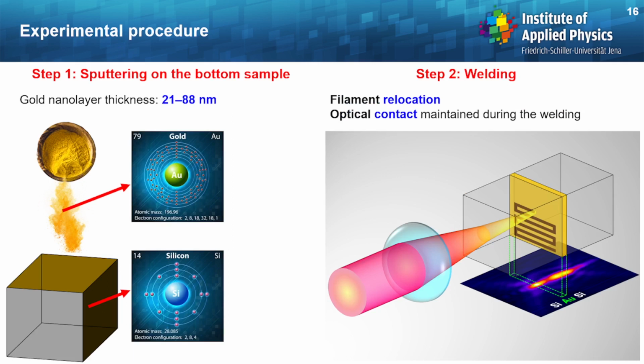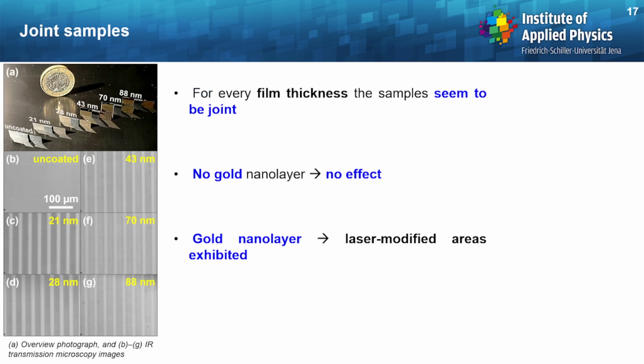So, basically the experimental procedure is now quite straightforward. First we do some sputtering on the bottom sample with gold nanolayer thicknesses between, let's say, 20 and 90 nanometers. And as a second step, we do the welding with the filament relocation, so we precompensate for the nonlinear focal shift, and at the same time, we maintain the optical contact during the welding. Okay, so here are the results.